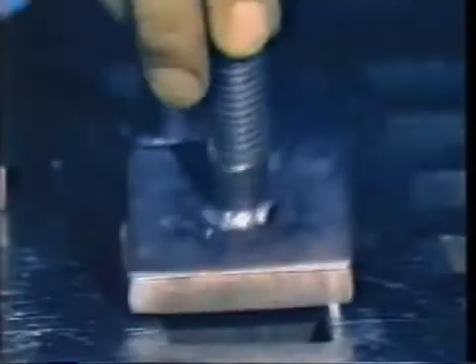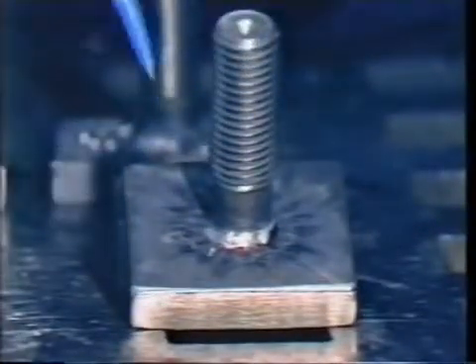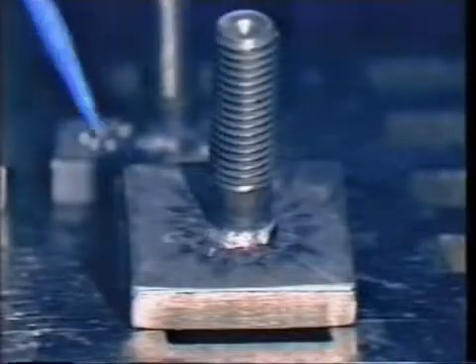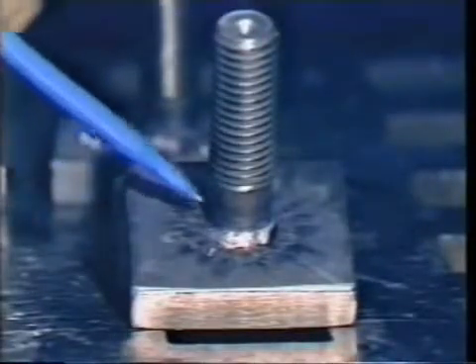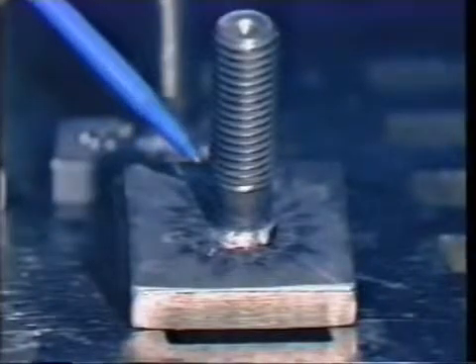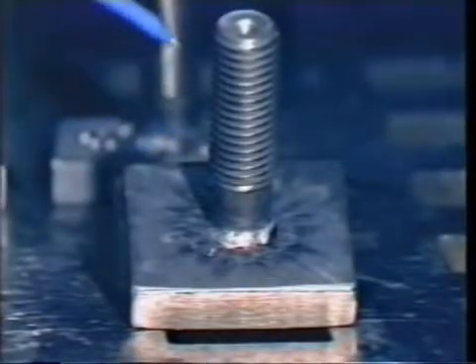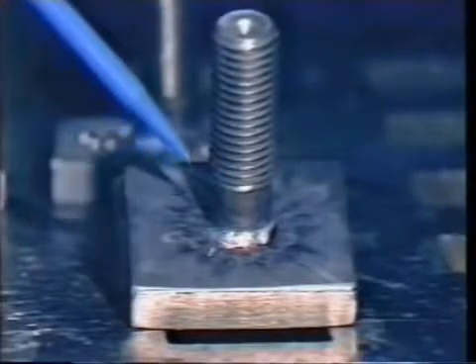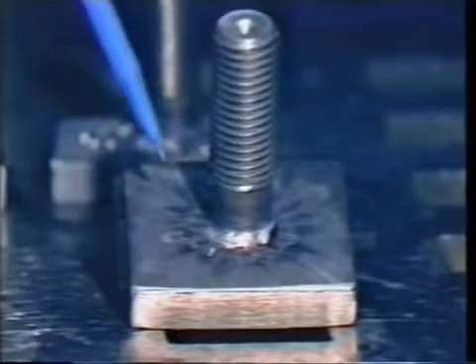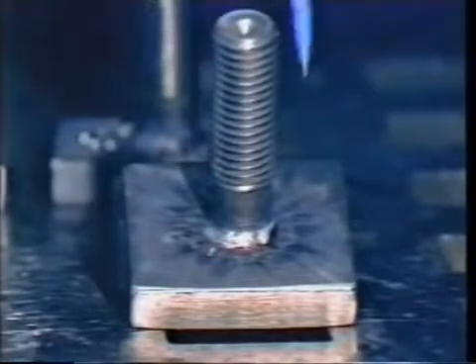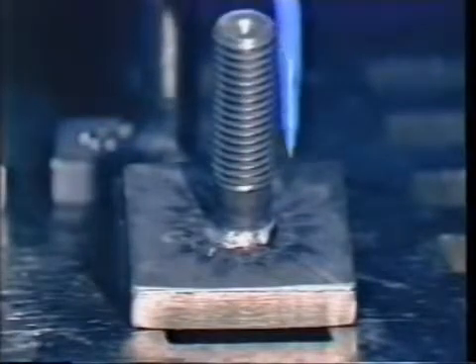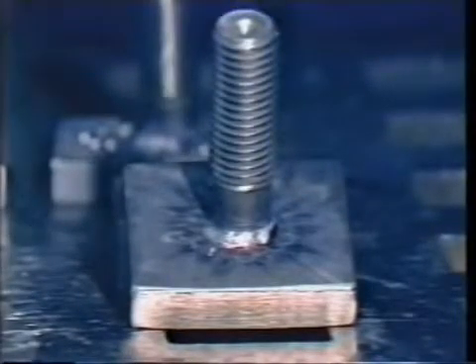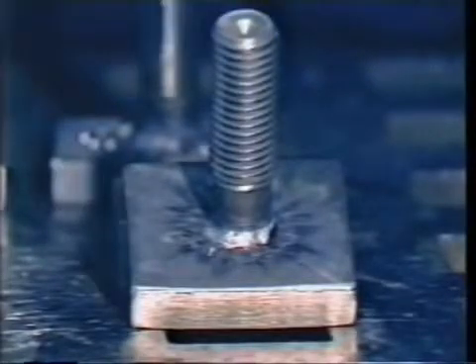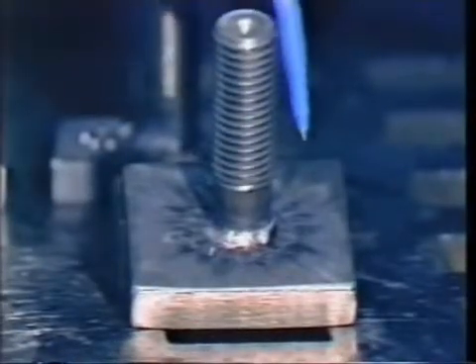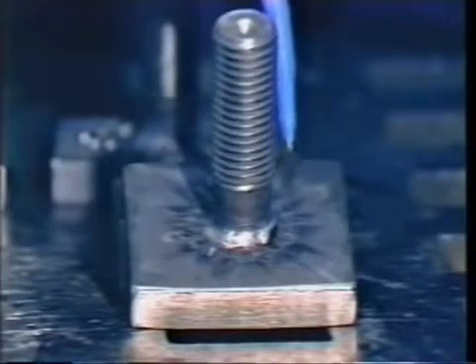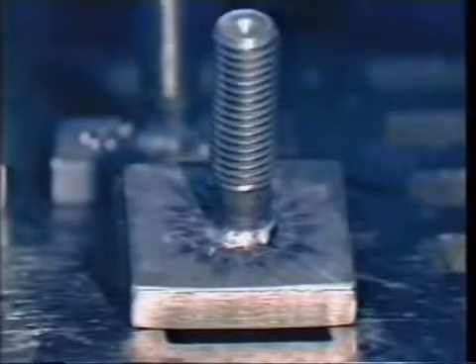The other one that gives the appearance of being too hot, with undercutting, was done at a normal amperage, but it had a restriction in the gun motion, either through not having adequate plunge set, or a gun that needed maintenance, or possibly the Tranquil Arc plunge dampener was set for too slow a dampening rate and the stud didn't get down into the base material. Checking the before-weld and after-weld length of the stud can give you a clue of whether there was a hang-up or insufficient plunge.